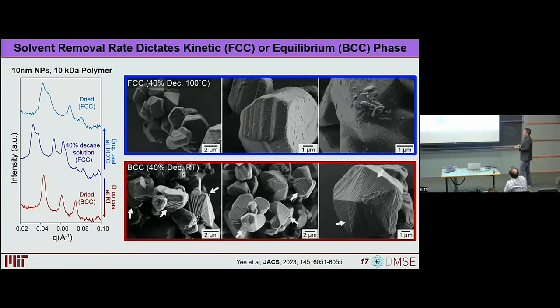We see quasi-hexagonal morphologies. We see sort of this five-fold pentatwin structure as well. So what that tells us is the overall shape of our crystallite is not changing even as the underlying unit cell changes. The other thing that's interesting, though, is that we see these very odd kind of chevron-like striations, which are pretty consistent across most of our particles. And this tells us something about mechanistically what's going on.